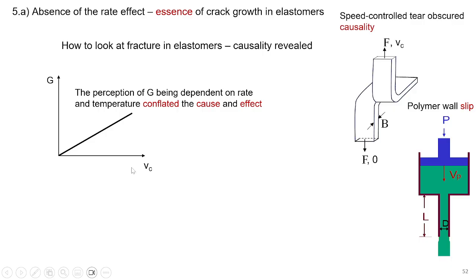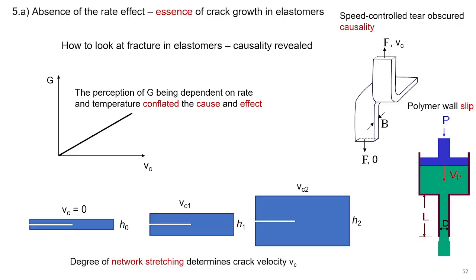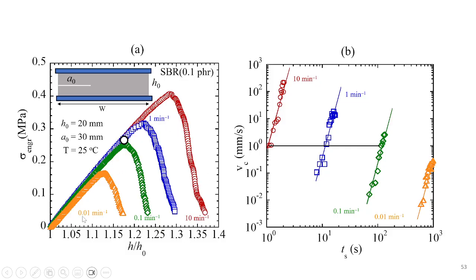So you can prove that. You can do this by simply loading them to different levels and watching how the speed of the crack changes with the load. This actually is a beautiful experiment. We used 4 different rates to stretch this pure shear experiment, the lowest rate versus the highest rate. In the region where they reach the same strain, the speed is the same. In other words, the speed of the crack is only determined by how much you have stretched. The rate is a variable that just tells you how quickly you get there.